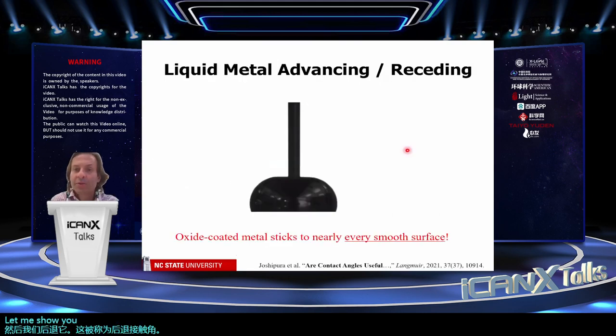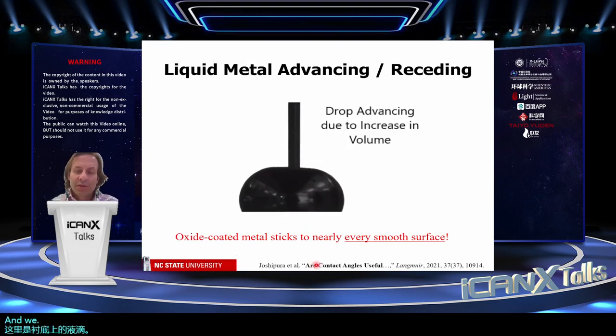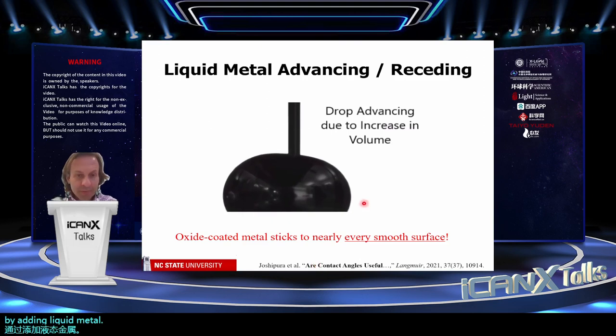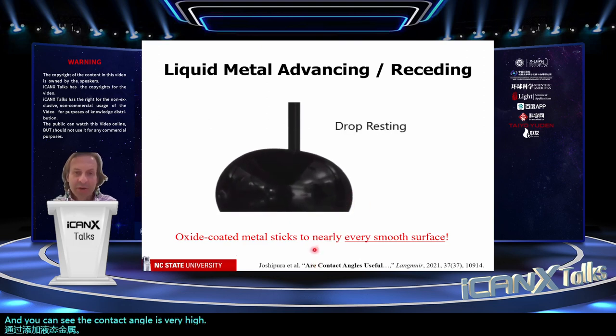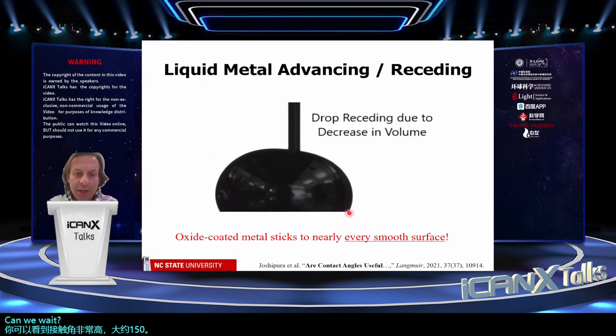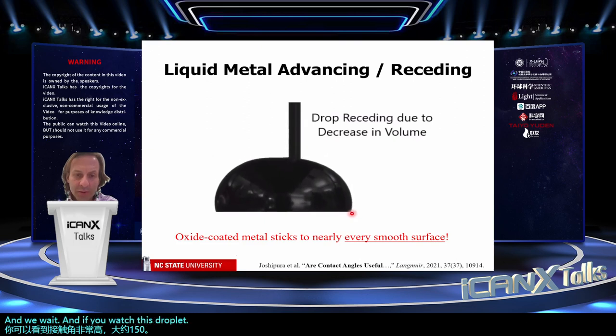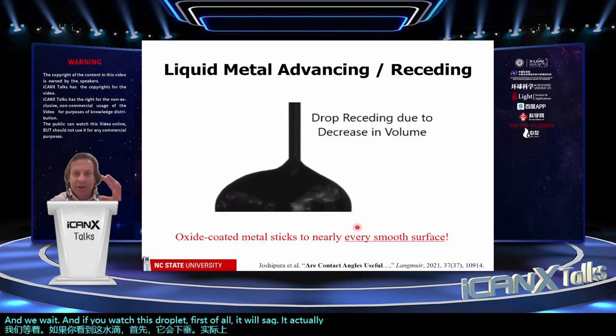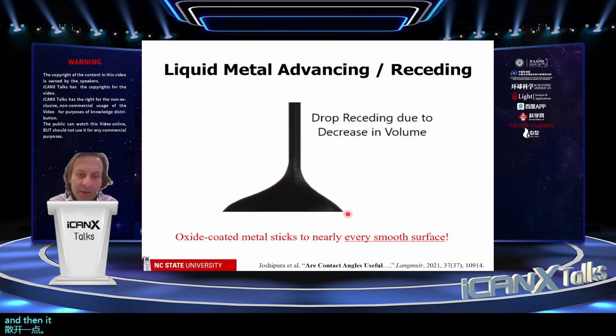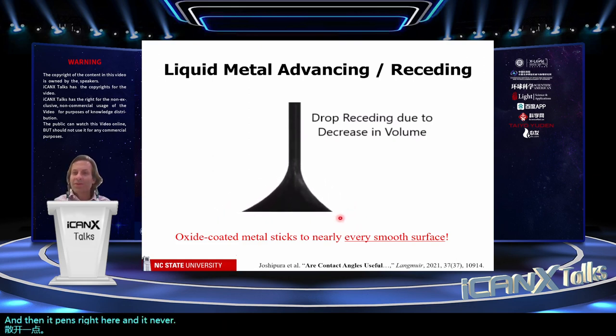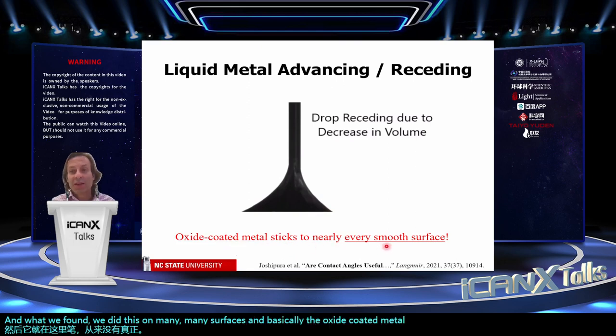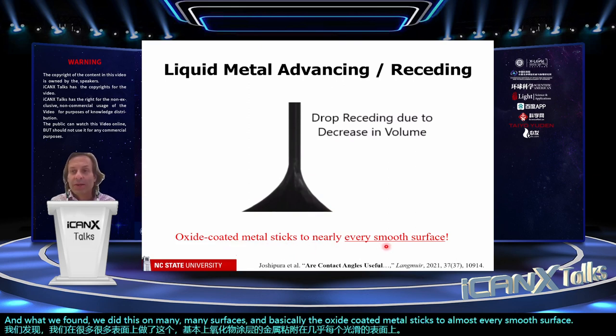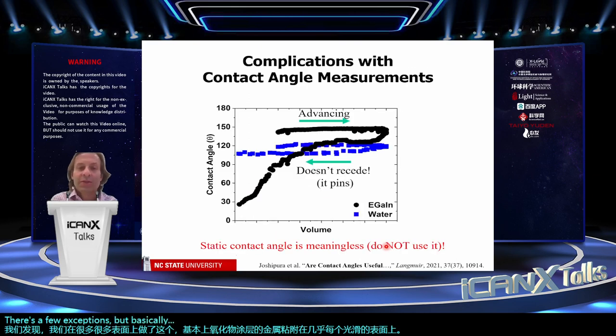Let me show you what happens with liquid metal. Here is a droplet on a substrate, and we advance it by adding liquid metal. And you can see the contact angle is very high, about 150. Then we wait. And if you watch this droplet, first of all, it will sag. It actually spreads out a little bit. And then it pins right here, and it never really recedes. We did this on many, many surfaces, and basically the oxide-coated metal sticks to almost every smooth surface that we tried. There's a few exceptions, but basically it sticks to almost every surface.